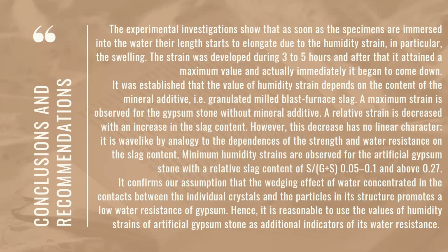The experimental investigation shows that as soon as specimens are immersed into the water, their length starts to elongate due to humidity strain, in particular the swelling. The strain developed during 3 to 5 hours, and after that it attained a maximum value, and almost immediately it began to come down.